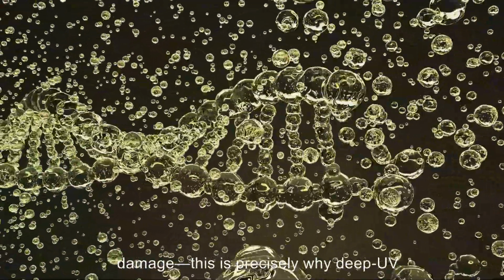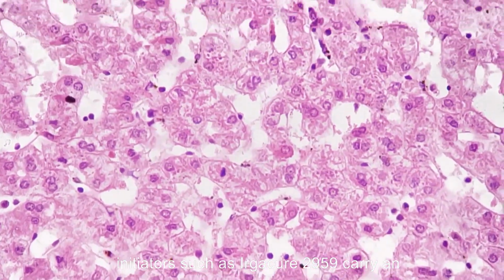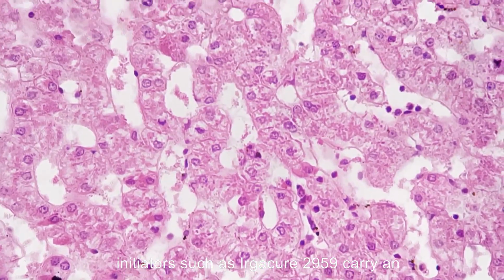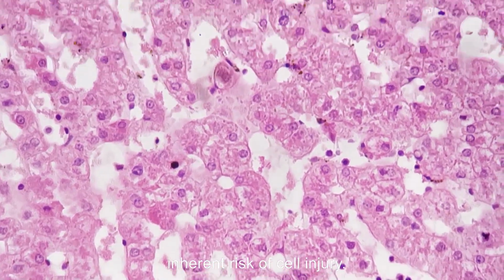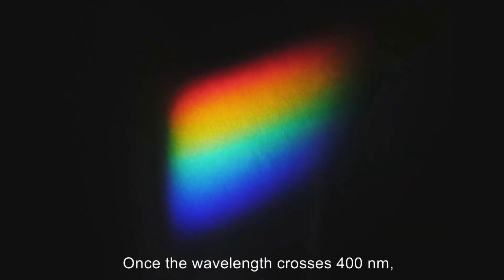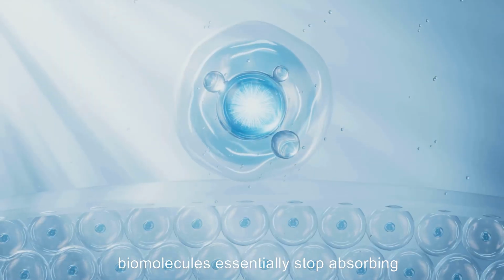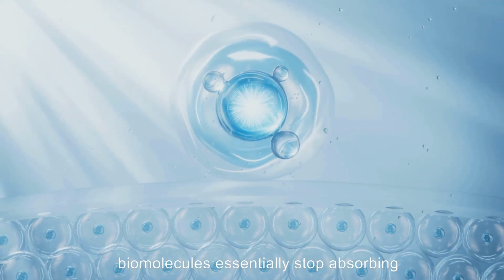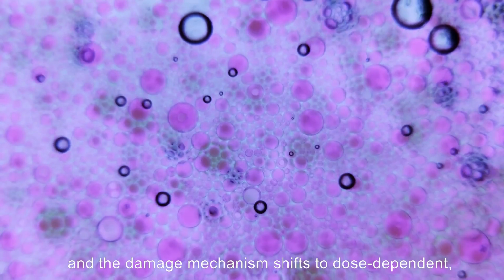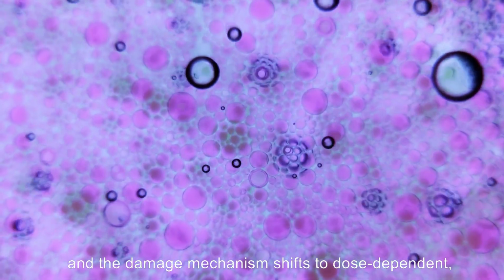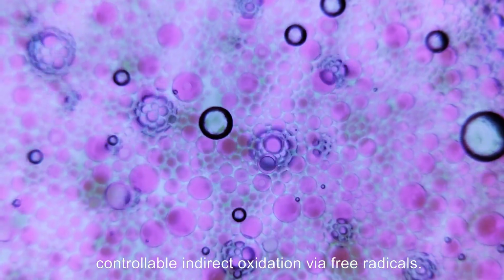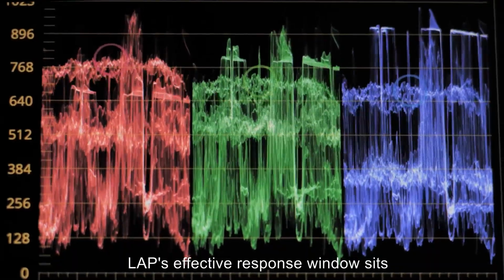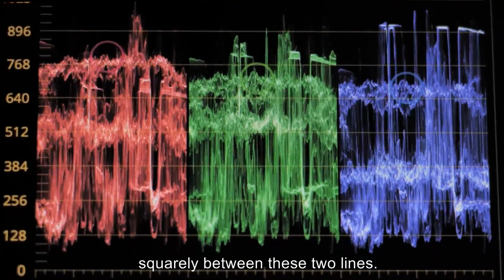This is precisely why deep UV initiators such as Irgacure 2959 carry an inherent risk of cell injury. Once the wavelength crosses 400 nanometers, biomolecules essentially stop absorbing photons directly, and the damage mechanism shifts to dose-dependent, controllable indirect oxidation via free radicals. LAP's effective response window sits squarely between these two lines.